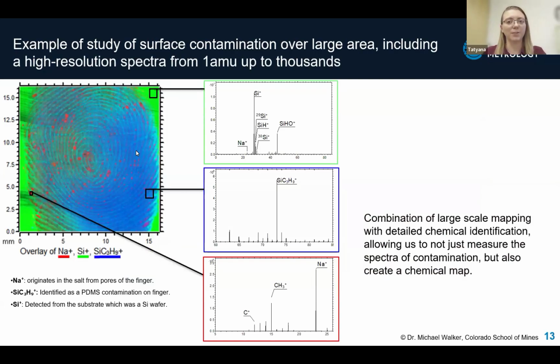I would like to highlight the essential capabilities of ToF-SIMS through the measurement results from different areas. I will start from this fascinating example of high-resolution surface contamination analysis. On the left, you can see a color-coded overlay map showing a distribution of 3 different chemical species across a 15 by 15 millimeter area of silicon wafer surface. As you can understand, this is a fingerprint. The map shows sodium in red, which comes from the salt residue from finger contact, silicon in green from the underlying silicon wafer, and organosilicon compound in blue, which is assigned to PDMS, a common silicon-based contaminant.